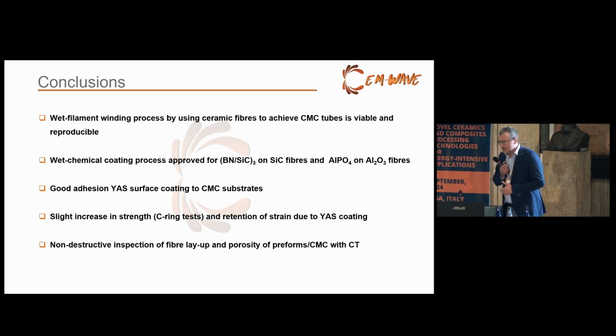And the thing is, with a wet filament winding process, we can achieve really nice CMC tubes independent of the material. We could do wet chemical coating both on silicon carbide fibers and on aluminum oxide fibers. We saw good adhesion from the YAS surface to the CMC substrates, and we have a slight increase due to the YAS coating. The good thing is that we can use computed tomography for very nice non-destructive testing, where we can look at different stages of the long manufacturing chain, and this is important to really keep an eye on your process, where you can do a lot of things wrong. Thank you very much.